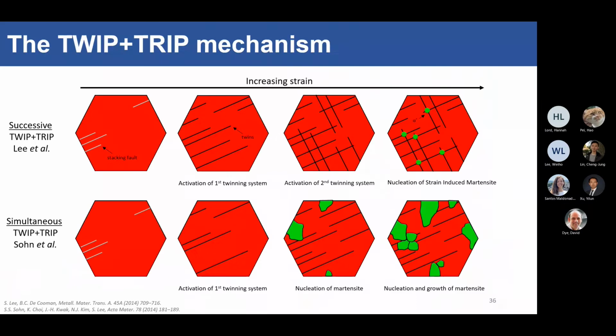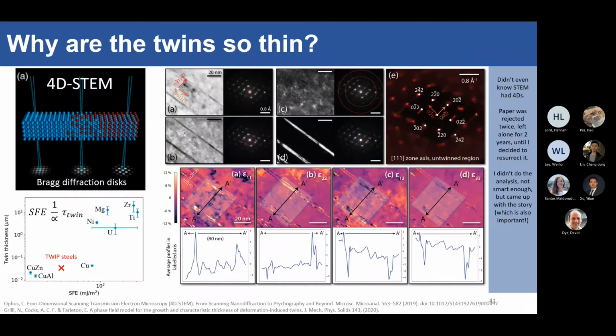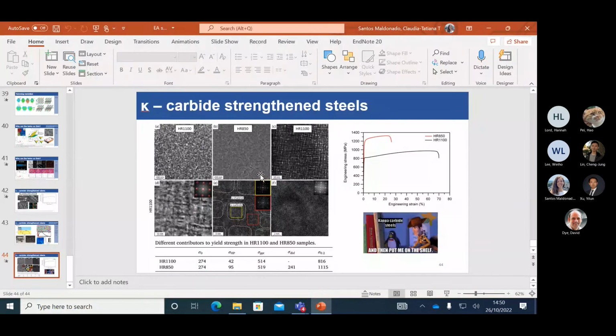I actually have a lot of little GIFs to present. Sorry, these are backup slides. Never mind. I think most of you know I said half the time I'm cleaning the melter, right? So manganese evaporates from the melt surface very easily. That's also a big problem in industry: when you have a very high manganese content, you lose a lot of the manganese to soot and so on. So fabrication is not easy from an industrial point of view, but in our small melter, you can top up a little bit of the manganese, so you do arrive at the manganese content that you want. But yes, pretty much that.